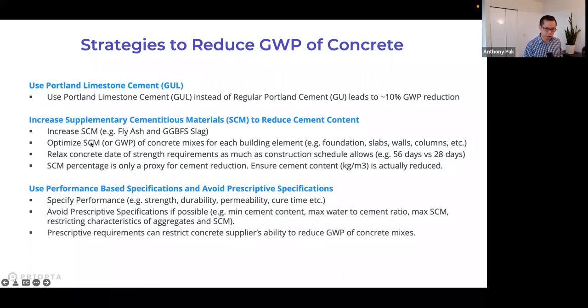Next is looking at reducing the cement content. So most of the emissions associated with concrete come from cement. And so if you can reduce the amount of cement used and replace it with supplementary cementitious materials, things like fly ash or slag, that can reduce the cement content and then reduce the emissions overall of the concrete. And one design strategy is to optimize the concrete mixes across each building element. So maybe for your foundation, you can have higher SCM content, whereas for the suspended slabs, you can't go as high based on curing times and the construction schedule, because this can affect the construction schedule as well.